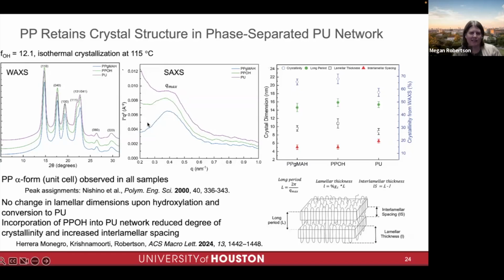From the small angle region, we can see that lamellar peak. This is going to give us these dimensions of the lamella. We have what's called the long period, the interlamellar spacing, and the lamellar thickness. All of those we can quantify. And again, if we compare our starting polymer, the maleic anhydride grafted, then the hydroxylated, and finally our polyurethane, we're not seeing any change in the structure of that lamella. The only difference we're really seeing is that there's more amorphous content in the polyurethane. So if we look up here at the degree of crystallinity, we see a drop for the polyurethane. And also, if we look at the interlamellar spacing, we see a bit of an increase, which makes sense if there's a higher amount of amorphous content.